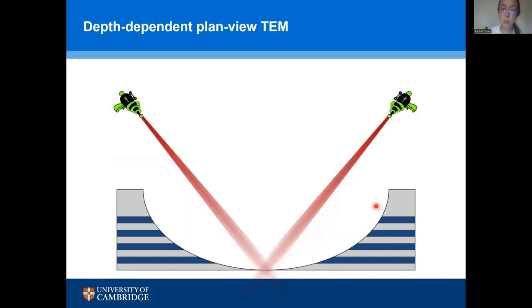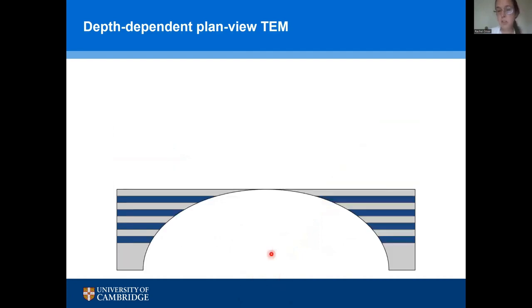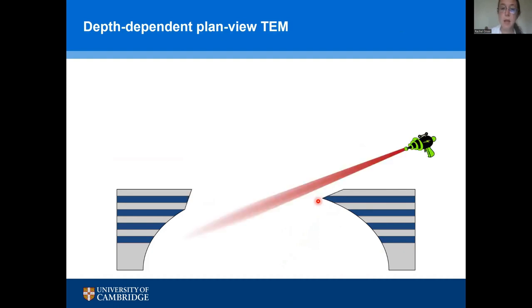when we make a TEM sample, we need a really thin foil of material. And we make that using an ion beam milling technique, where we typically have two ion guns coming from opposite angles, milling away at the material to make a thin region here at the center of the material. And we'd normally just look at that in the electron microscope, and we'd maybe have thin enough material to see the porosity just at this edge here, for example. And if we then come in with the ion gun again, having turned the sample over, we can access deeper layers by milling further into the structure.